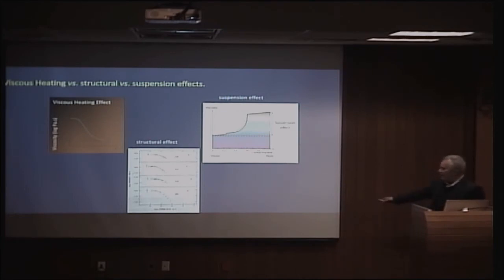So here you see what happens to the viscosity as a function of strain rate. As I push into the yellow zone, I fall off the edge. I fall off the cliff of Newtonian viscosity, and I have what we call shear thinning, well described in the polymer literature, well described in many literatures of rheology. And basically, these materials are sheared out of equilibrium. They're sheared out of existence. You can literally mechanically push the liquid out of thermodynamic equilibrium using a big press. Okay? And this, of course, happens about the same time that this happens, which makes things very complicated.